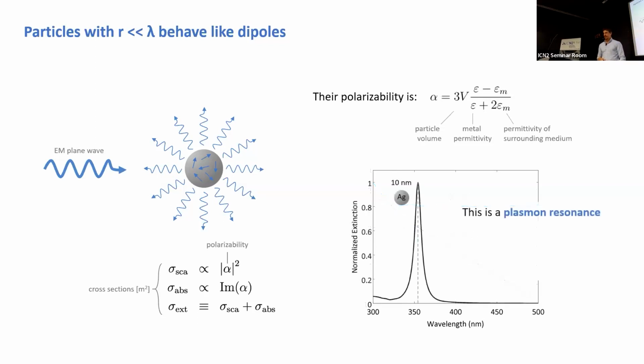And so a silver nanoparticle in vacuum extinguishes light, scatters and absorbs a lot of light at 350 nanometers, huge peak. This is what we call a plasmon resonance. That's to answer this whole torture that I imposed upon you, was to answer the question, what is a plasmon resonance? What do we mean by that? Now, this is a plasmon resonance. However, it is a plasmon resonance for a very small spherical particle of a good conductor in vacuum. And you actually have to put all these caveats in.